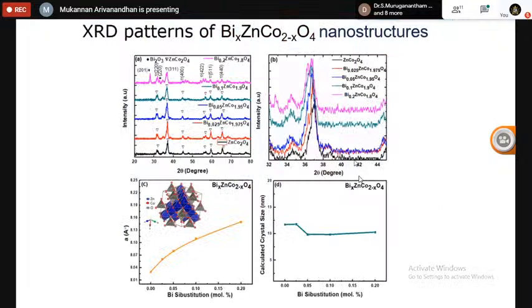Then the sample was subjected to X-ray diffraction analysis, and the structural patterns confirm the zinc cobalt oxide phase. Up to 10% bismuth it's a pure phase, and when the bismuth content increased beyond 10%, a secondary phase was obtained. This shows that up to 10%, bismuth has been effectively substituted at the cobalt site, showing the alloying effect. Then, due to exceeding the solid solubility limit, a secondary phase was obtained. All the structural parameters have been confirmed.